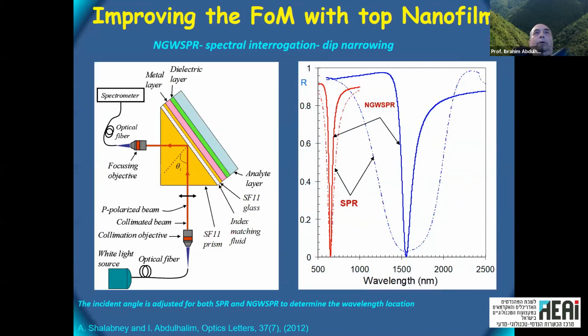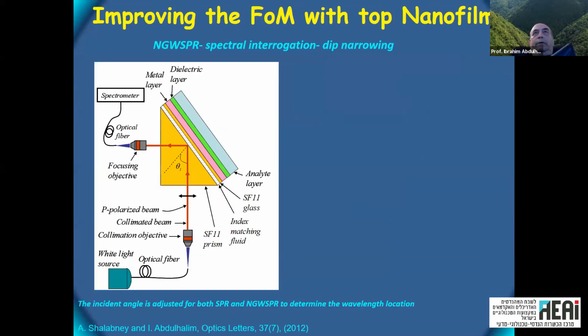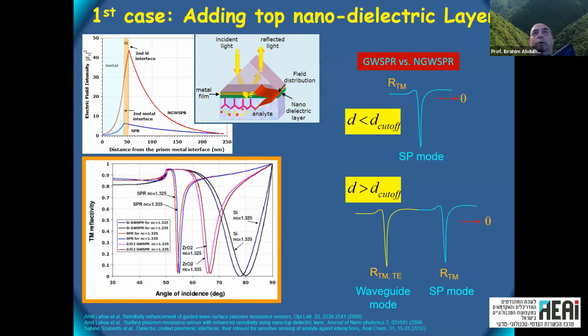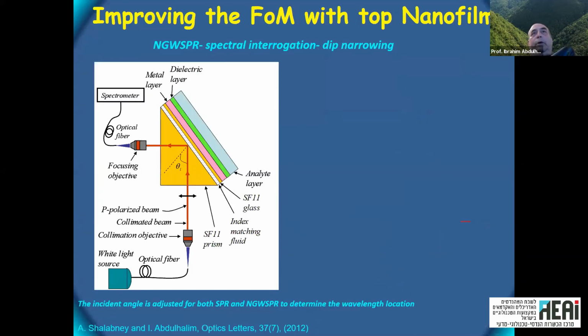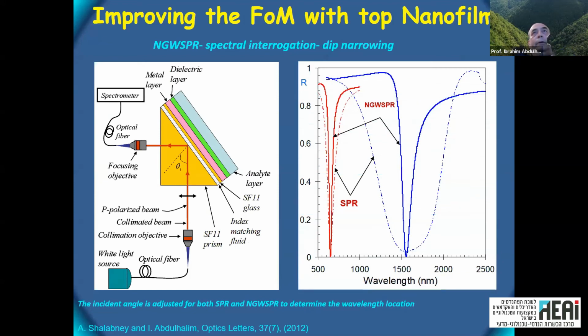Then we find quite interesting result. As you see here, the resonance becomes wide. So the figure of merit might not change, actually. It almost does not change. The sensitivity is better, but the figure of merit is the same. Although you gain in the field, that's another advantage. But if you want to improve the figure of merit, we need to go to the spectral mode.